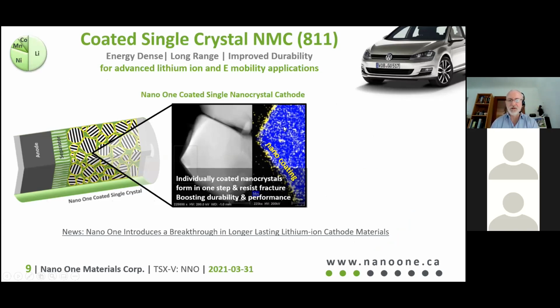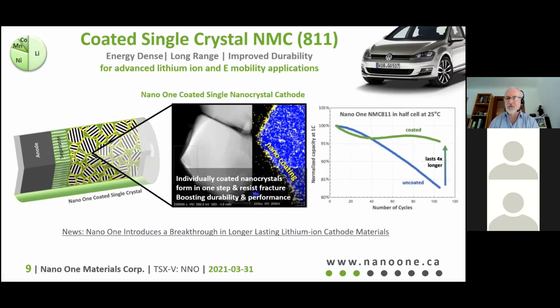And the blue and yellow picture on the other side is an elemental map. We can map the elements in this. The blue is nickel in this picture, and this is the crystal edge. And you can see the yellow is the coating material, and it's come to the surface. You can't see the scale bar on this picture, but this coating is very, very thin. It's of the order of hundreds of atoms thick on the crystal, and it's on each individual crystal. The effect of this is to improve the durability of the high nickel material.